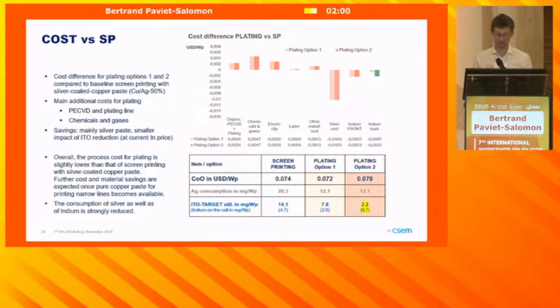Of course, we expect this difference to be even greater once even cheaper copper paste becomes available on the market. And at the end of the day, what is interesting is that with the approach we propose, you can reduce the indium consumption below 1 milligram per watt peak at cell level, which is also very important for the future upscaling of heterojunction as a main technology.